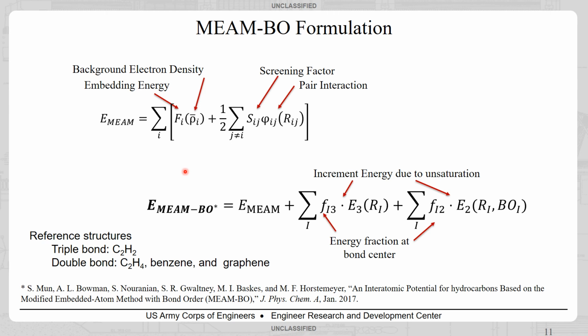So for example, if you take an atom that's within a cluster of chains, that would have a higher embedding energy or background electron density because it's in that cluster of atoms, while if you took one that's at a free surface, it would have a lower energy. So you can capture locality effects of your atoms, whether they be at free surfaces or in clusters of atoms. So it gives a higher accuracy, and that's why the MEAM can capture things like void formation energies and surface formation energy and chain-to-chain friction very well, because of this term right here, which is unique to the MEAM potential. And then we can add bond order to the existing MEAM formulation, which then captures fractional bonds for double or triple bonds. This particular work, since we're just focused on polyethylene, these bond terms are zero since we have a completely saturated polymer, but we are working on more complex polymers that utilize these terms here.